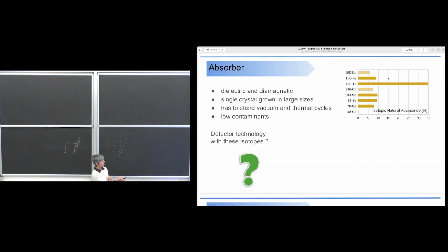So in the past, calcium fluoride crystals were used for the study of this isotope. This isotope has advantages from the point of view of the nuclear models because it is easy to evaluate the nuclear matrix element with the shell model. And so for a while it was really considered by the community, but the problem is that the possibility of enriching it, there are techniques, but they are very, very inefficient. So it would be extremely expensive, much more expensive than what you think. Orders of magnitude more than the others.